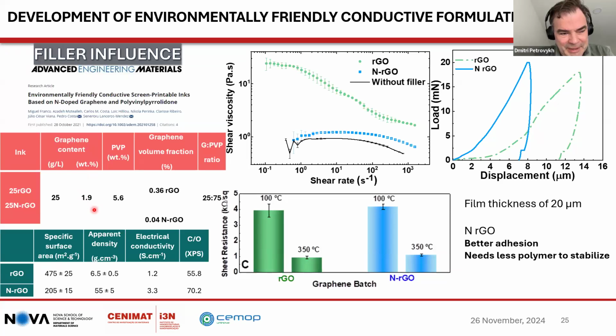Maybe another aspect. Is there a difference in ink formulation for conductive inks versus inks that use semiconductor or oxide materials? In this case, semiconductors are quite different because you also want to preserve their carrier characteristics and mobility. So you need to use the minimum amount of binder possible, because adding a binder can also degrade the semiconductor performance. This is another balance for those types of inks.